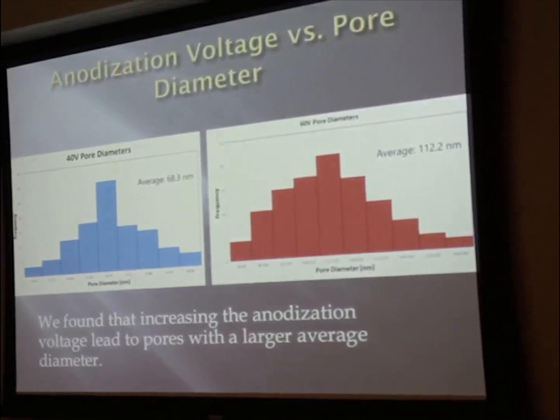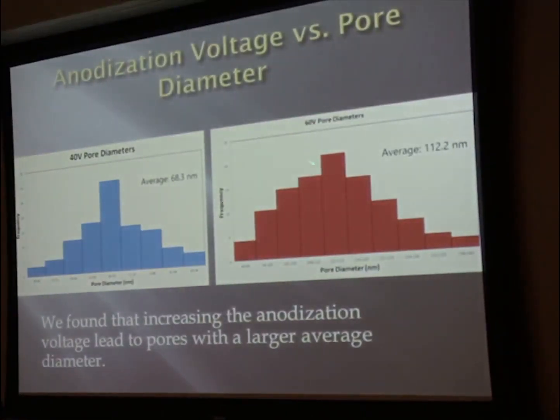These two charts show 100 pores measured for each of the samples, both 40 and 60 volts. On average we had about 68 nanometers for the 40 volt with a pretty Gaussian curve, and then 112 here for a not as Gaussian but still pretty Gaussian curve for only about 100 data points. If you took more data points, you would expect it to get more normally distributed, and we get closer to an actual average. So you can tell lower voltage, lower pore diameter; higher voltage, higher pore diameter.